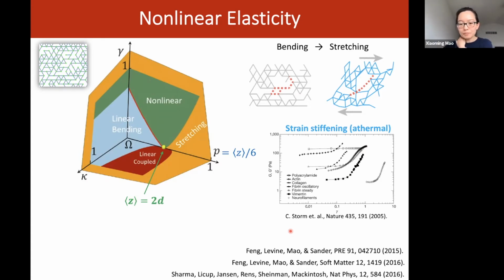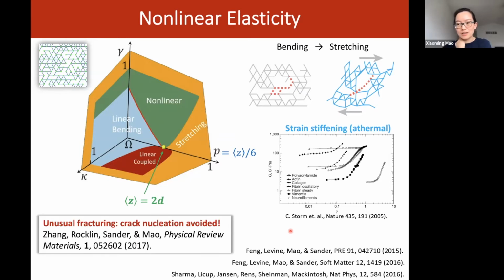To finish this part, I'd like to mention that we have also studied fracturing of these fiber network materials, and we saw that their fracturing process is very special. Basically, the crack nucleation that is typical for many brittle materials is completely avoided in these fiber networks because of this criticality in their rigidity. More details are summarized in our paper here.